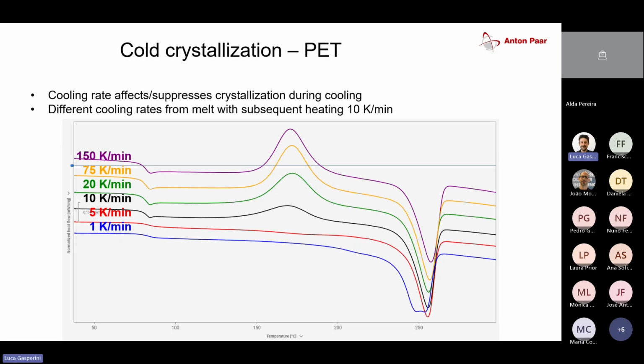That's the cold crystallization. Meaning that when I cool the sample down from the melt at up to 5 degrees a minute, the sample has enough time and is relaxed enough that it can actually crystallize during the cooling. But the higher the cooling rate was, we saw the crystallization peak during heating, so cold crystallization, meaning that the sample didn't have the time and space in order to crystallize during the cooling process.